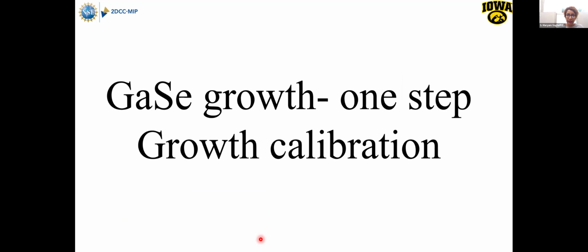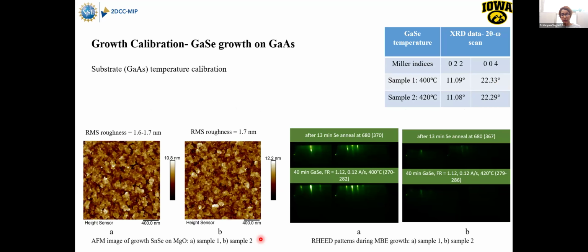And then we did the same things for growing the gallium selenide. And this is the result we have. That recipe is already developed in Professor Law's group. And here we could grow different thicknesses of gallium selenide.